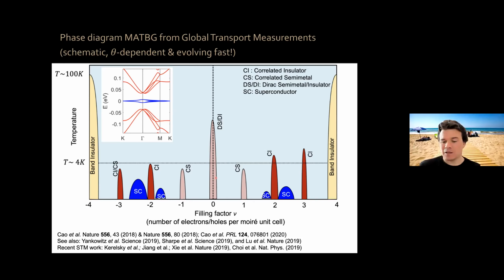Now, the interesting thing that we saw back in 2018 is that at 2 electrons and 2 holes per moiré unit cell, you have a correlated insulator state. Since then, other studies, both by our groups and by other groups, have seen that quite often you also see correlated insulator states at 3 electrons, sometimes at 3 holes per moiré unit cell. And you see also correlated states, not insulators, but correlated semi-metallic states at 1 electron, and sometimes at 1 hole per moiré unit cell. And you can have even an insulator state also at 0 sometimes.